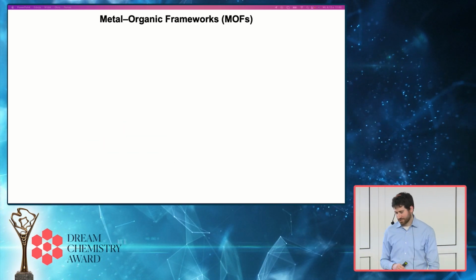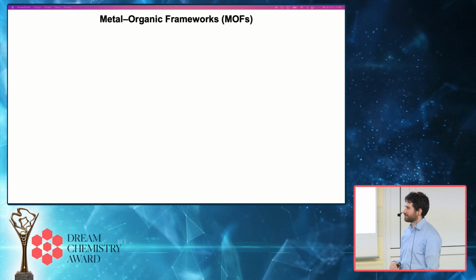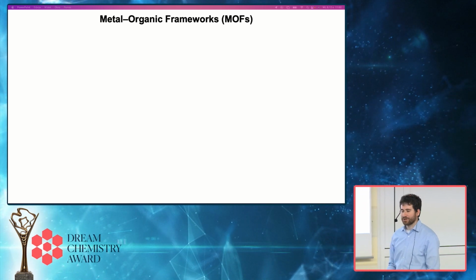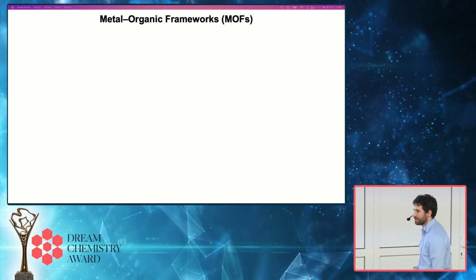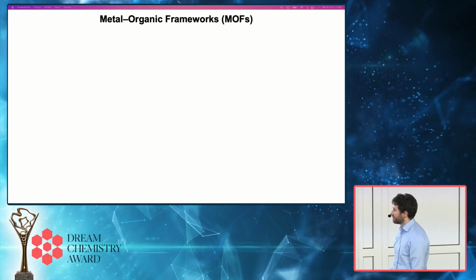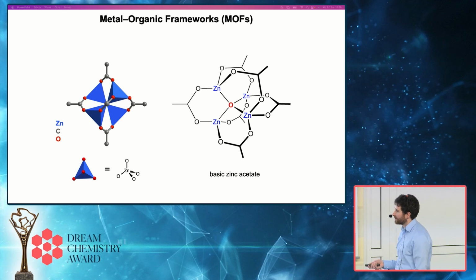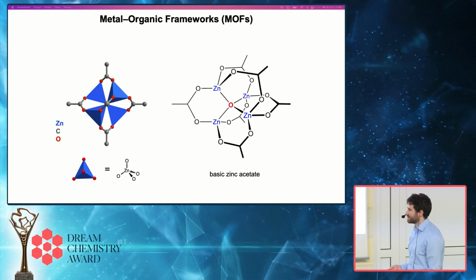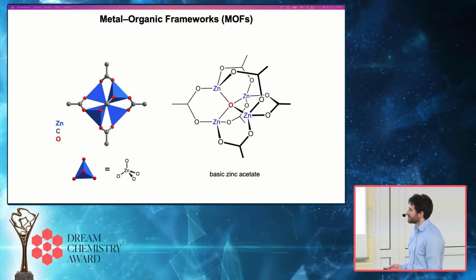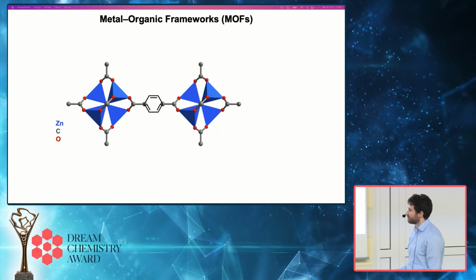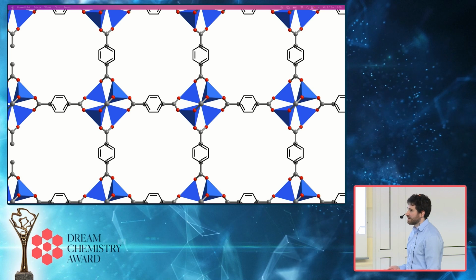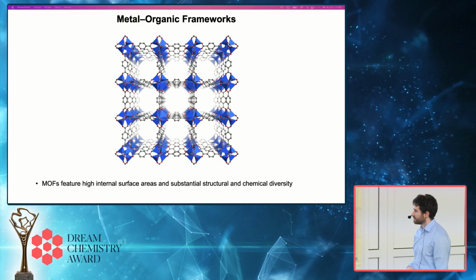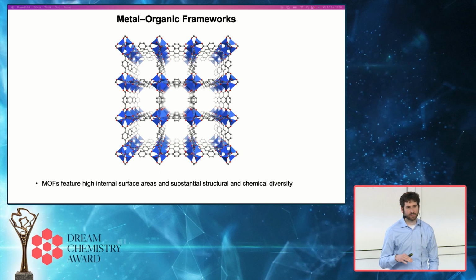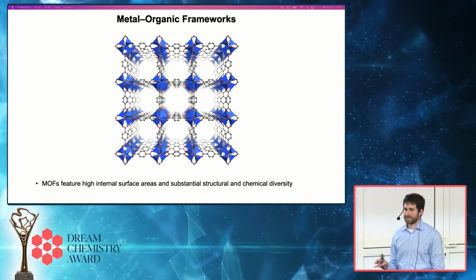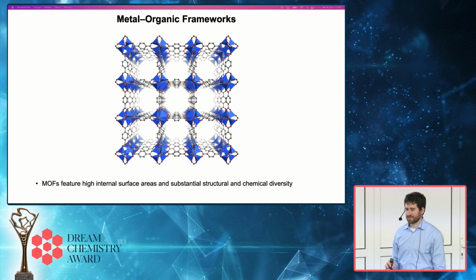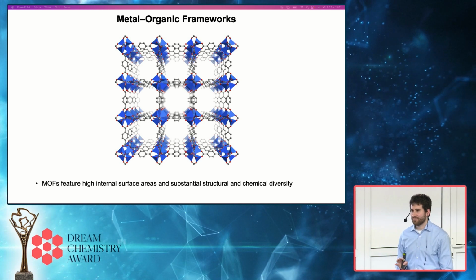Before getting back to that, I'll just mention some ways in which we've been able to generalize this approach beyond just metal organic frameworks to other classes of porous materials. Since Carl did a really nice job of introducing metal organic frameworks, I'll just briefly reiterate that these are materials that contain small inorganic clusters or metal cations that are linked together by different kinds of bridging organic ligands to form three-dimensional porous materials. The reason we were excited about extending this approach to metal organic frameworks is that there's something like 90,000 metal organic frameworks that exist currently in the literature compared to about 240 zeolites.